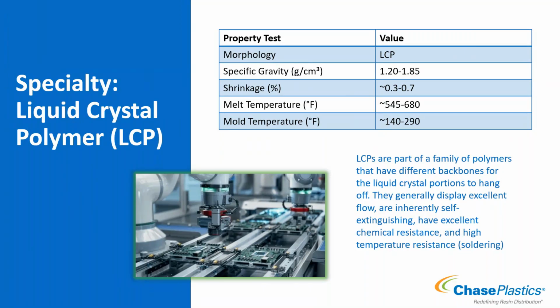Some value proposition, or the reason you would use something like an LCP, is it has excellent flow capabilities, so you're able to fill thinner parts than you would be able to with other standard products - really, really great flow performance. It is also inherently self-extinguishing, so you don't have to add anything to it, you do not need to give it a flame package. It will inherently self-extinguish, and so it would achieve a V0, 5VA rating through UL without anything needing to be added. It also has excellent chemical resistance and good, really high temperature resistance.